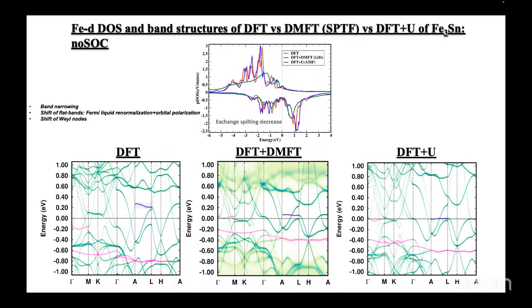Then we analyzed further with just the static correlations, where we do not see the effect of Fermi liquid renormalization. Here the only band shifting that we see comes from the orbital polarization, where the 3d band shifts towards the Fermi level. But we also witness the shifting of nearly flat bands slightly above what we observed in the DFT. This shows an overall picture of how the static and the dynamic correlation impact our band structures and physics.